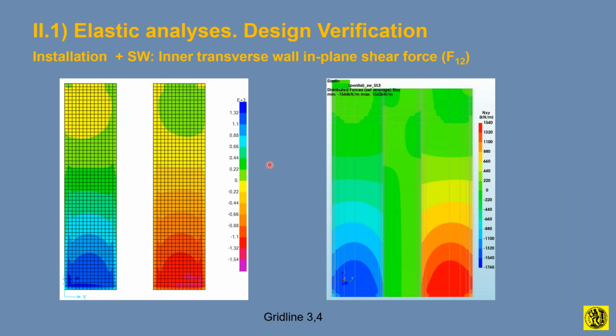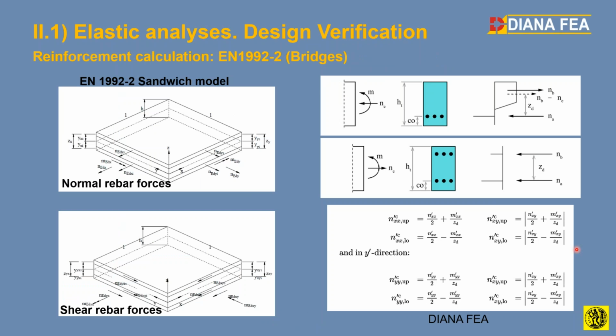And again, we can see that the shear forces define a fairly constant distribution at the base, but from then on they die out. Practically whatever happens is in the bottom part of this caisson. Of course, we also solve the plus or minus 1 meter differential, which gives us the head to look at the moments and the reinforcements longitudinally and transversely, and they check.